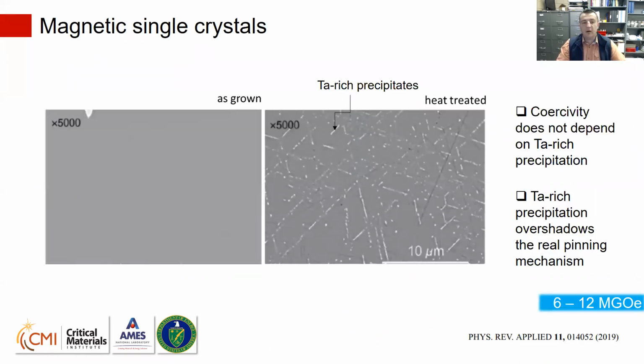So we decided to figure out why it is showing extrinsic magnetic properties. Why is it showing coercivity? And when we heat treated our single crystals, obviously we found that the material is not single crystalline anymore. However, there were precipitates, and we thought that they were pinning sites. Unfortunately, there was no dependence on tantalum. Those precipitates were basically tantalum, or very rich with tantalum, but the magnetic properties were not dependent on tantalum. So we decided that this is just camouflage, or something showing that something is happening in the single crystals.